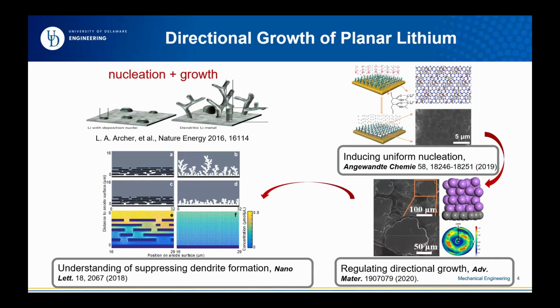We use some polymer to make the nucleation of lithium ions uniform. In that case you avoid developing the kind of structure that would be dangerous. We also use graphene oxide to induce and guide the lithium growth on the lithium metal. Here you can see there is no dendrite formation, but a flat surface. We also use some calculation tools to understand what is behind it. Here is a simple comparison of two columns. On the left side, we apply a physical porous structure, and on the right side the dendrite is still free to grow.